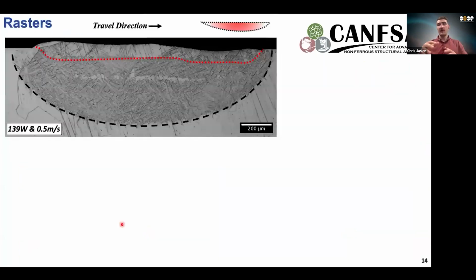And so now moving on to a case that's maybe more applicable to an additive manufacturing build, we're looking at rasters or laser tracks on top of the material. And so we see a very similar material response, where we've got our melt pool denoted red up here, and then significant amounts of this TRIP product has formed in this heat affected zone region underneath the solidified material.